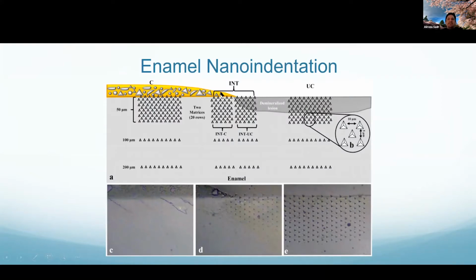We'll look at the very interface, let's say the edges of the sealant. We're looking at the edges of the sealant outside, and that is, if you look at the fissure anatomy, you see a lot of times, it's not only at the base of the fissure, but these initial occlusal lesions are also sometimes spread over that entrance of the fissure. But just putting a resin over that is not going to remineralize it, or it's not going to really help in remineralization. So anyhow, this is the research specimen preparation where we looked at the nano indentation at the edge and away from the edge by a few micrometers, right?